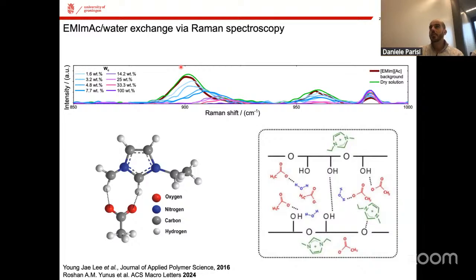We basically check what happens to the solvent when we add water in the presence of cellulose, rather than looking at the cellulose when we add water. So what we witnessed is that this peak here, which basically relates to the vibration of this group here, so it's basically the carbon-oxygen group of our ionic liquid. As soon as you increase the water amount, this peak becomes weaker and also shifts towards larger Raman shifts, or, let's say, smaller length scales.